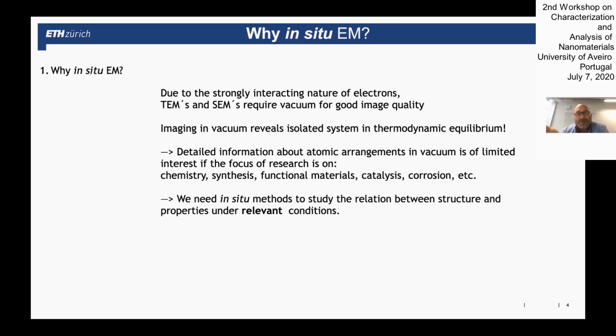And then when you have this possibility, then you can study your materials under relevant conditions. Like, for example, when you study catalysis, and I will give a talk about such things tomorrow, we can look at the material while it is in a relevant state. And then we can correlate the structure with a specific function of a material. We can get this important structure function correlation much better than if you just look at atom distributions in vacuum.